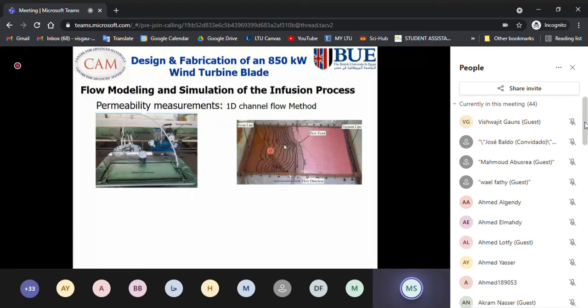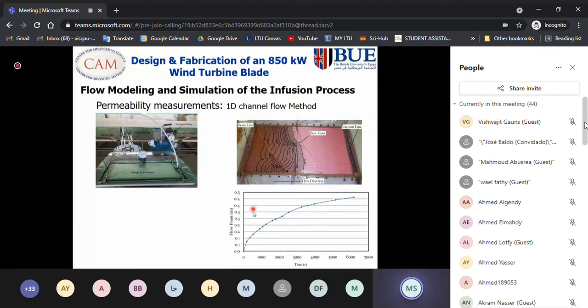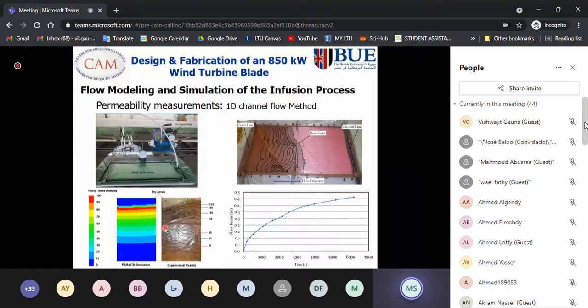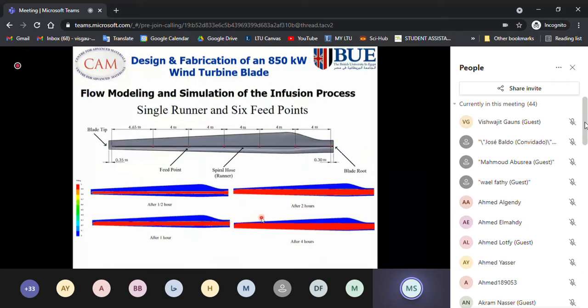So we measured the permeability of the fabric that we used. Basically, we measure the flow as a function of time. We use the PAM-RTM software to do the simulation of the flow process, and then we start to examine different strategies.